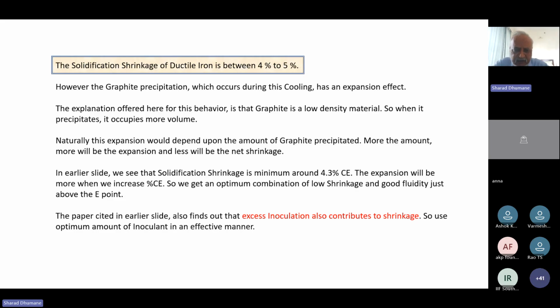Since we are talking about optimum inoculation, how do we decide whether it is excess or it is less? I think the best way to go about it is that you see your micros, not 1 micro, not 10 micros, not 50 micros, you see hundreds of micros. Every day you take out a few samples. Over a month, you will have seen hundreds of microstructures, and then you will realize that if your inoculation was on the lower side, then you see carbides and other undesirable phases, and you realize that yes, you had less inoculation in those heats.